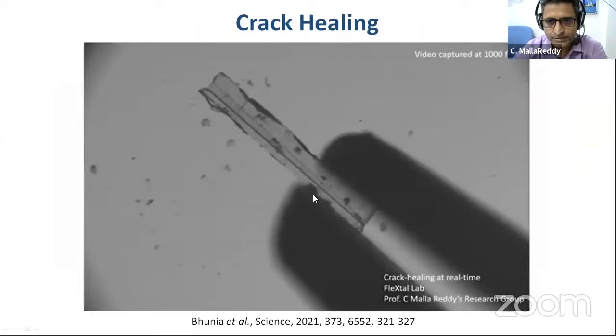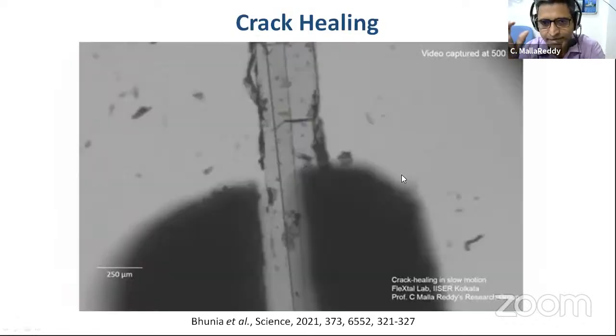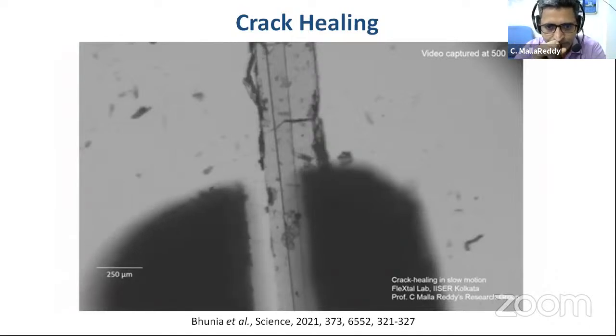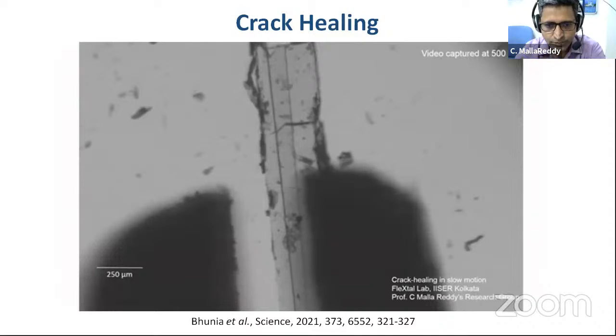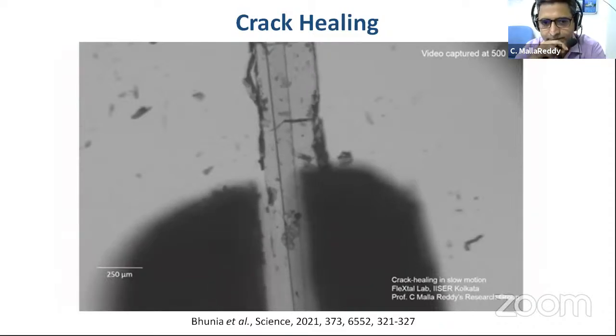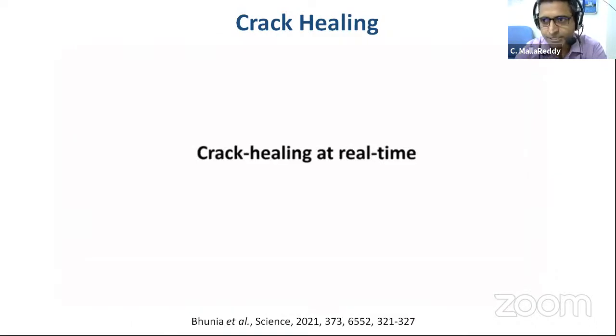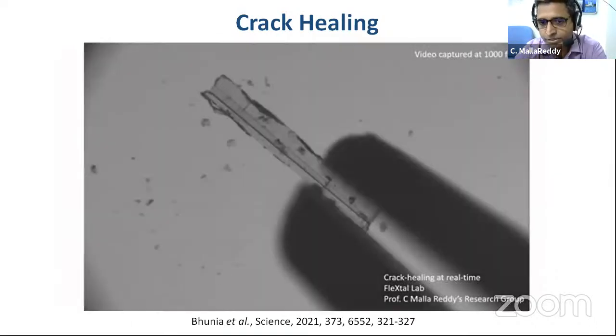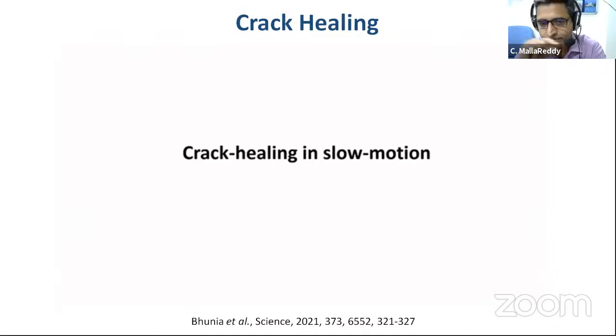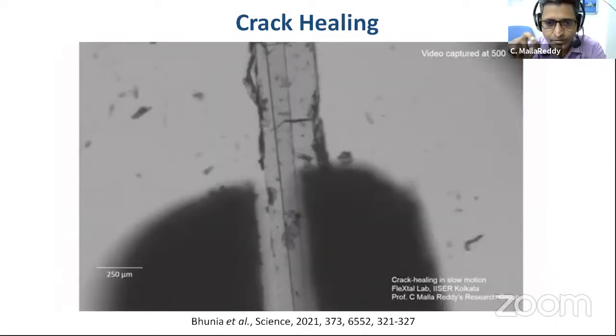As you can see here, that's how it happens. If you just press, then you have a crack, and then it generates. So this is slow motion again. If you push on top of the crystal, you have a crack, then you release it, and this crack completely goes off, and you don't see any sign of crack there. So it is a very clean healing. This is what makes these materials very interesting, because it is also very, very fast, and it heals almost like atomic level perfection from these images.